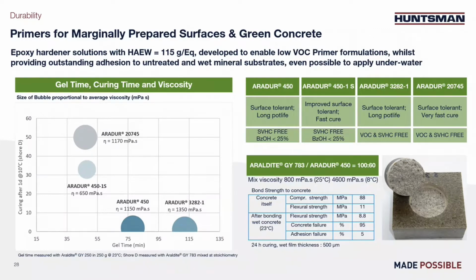On the right table, a few data on the bond strength to concrete. Basically, with pull-off tests, we can see that the failure is not adhesive, but mostly cohesive, within the concrete, proving the outstanding adhesion of the system onto the wet concrete.